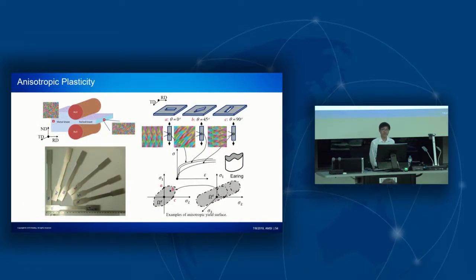After we have defined the growth of the yield surface, we may also need to define the shape of the yield surface. Because for most of the rolled sheets involved in the forming process, the grain distribution is no longer uniform, and they have some preferred direction. The result is when we perform the standard uniaxial tension test for the coupon cut in different directions with respect to the rolling direction, we'll end up with different stress and strain curves.